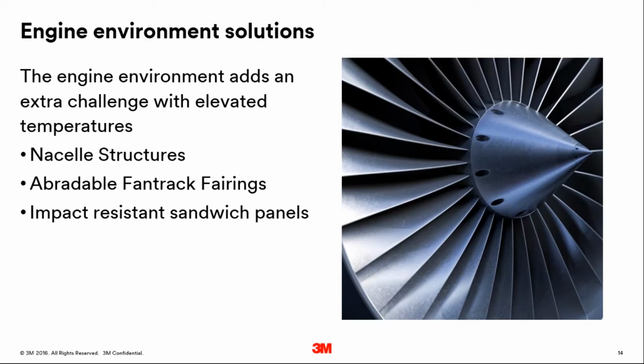Low-density void fillers are used as fan track liners within the engine casing, where we apply the low-density void filler and then allow the tips of the blades to wear away some of the fan track liner to create a very high tolerance gap and enabling very high efficiency. We've also developed impact-resistant sandwich panels using a combination of 3M adhesive and low-density void filler technologies. And these enable us to deliver solutions for managing blade release events.